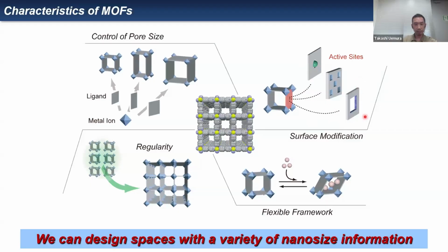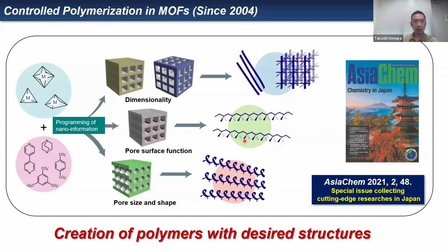Surface modification is also possible. High regularity because of the crystalline nature. And sometimes they show a flexible framework upon guest inclusion. So this means that we can design spaces with a variety of nano-size information. Here you can see our research interest. We can program the nano-size information, such as dimensionality, pore size and shape, by changing the combination of these two components. And after the introduction of the monomers in the MOFs and subsequent polymerization, we can obtain the polymers reflecting the host structure information. So by using this technique, we can prepare polymers with desired structures.